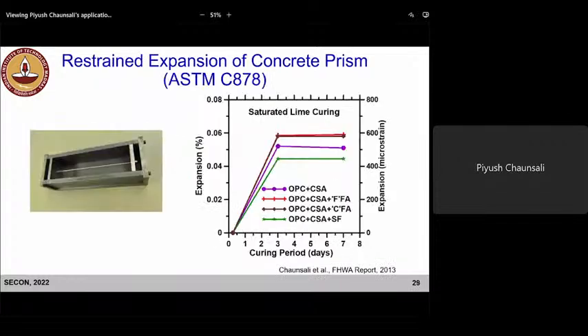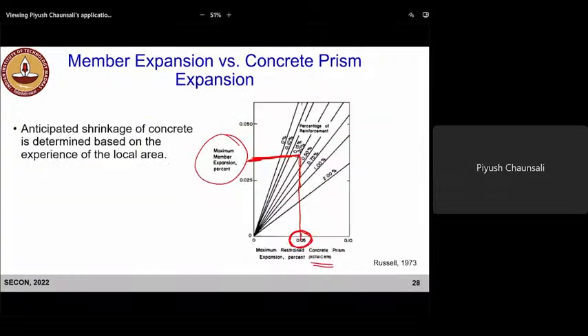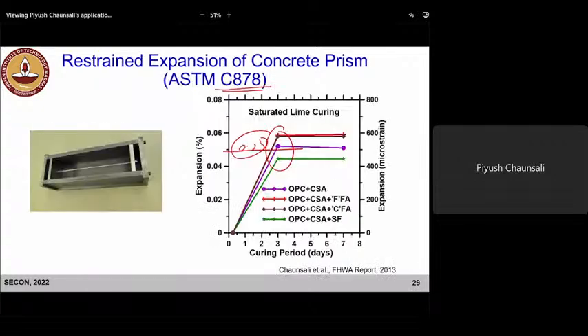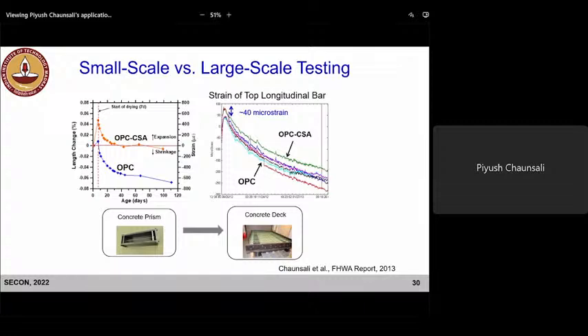So what is this C878? This is a simple test. You have a reinforcing bar and you pour the concrete, and then it is in restrained condition, and you measure the expansion. Through this expansion basically we can design. So if in this case the expansion is 0.05, roughly, let's say here, these design charts can be used. We can derive, for this much compensation we want, depending on the reinforcement, this much restrained concrete prism expansion, and then design the mix so that we get this much expansion here, 7-day expansion. So that's how we design this shrinkage compensating concrete.